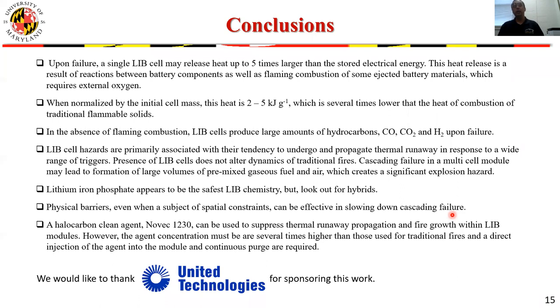One thing that I'd like to mention that I forgot to mention during discussion is that sometimes people state, and I've seen it in several presentations, that the batteries themselves generate enough oxygen to combust the hydrocarbons that they generate. That is not an accurate statement. The batteries do release a small amount of molecular oxygen, but it's nowhere near enough to combust the released hydrocarbon products. So to get this flaming combustion, to get the full energy out, you need external oxygen.